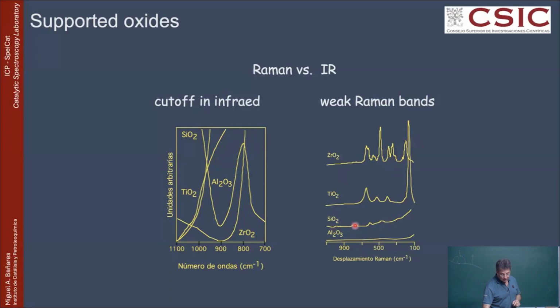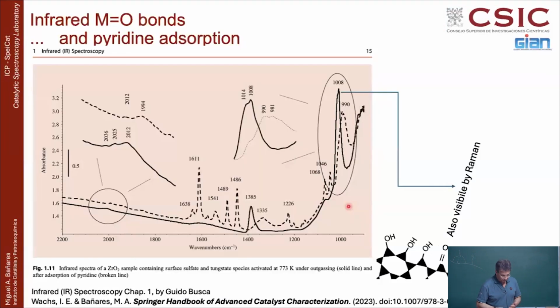That can be a problem on zirconia or titania, but you can see a lot of things. On silica, you get very weak bands. Gamma alumina is practically flat. There is hardly any signal. So you can see things very nicely. How nicely? Well, Raman spectroscopy, even when it is a weak effect with a weak signal, if you have like 1% vanadium oxide, molybdenum oxide on these materials, you will see the Raman bands of these supported oxides. This is unthinkable on infrared because with 99% of the support, this 1% of the supported oxide has a big problem going through the cutoff of the very strong absorption.